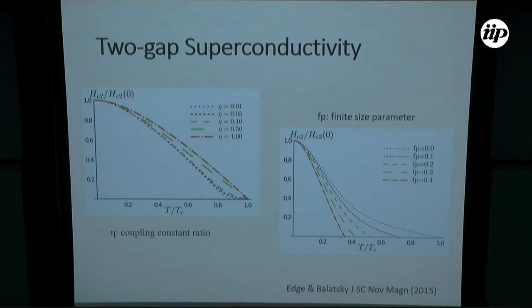We see, like this red curve, more of a negative curvature, and this can be due exactly to the fact that we are in a set of parameters that does not allow us to distinguish the two gaps. So it does not exclude the presence of two gaps, but probably the set of parameters is hiding the presence of the two gaps.